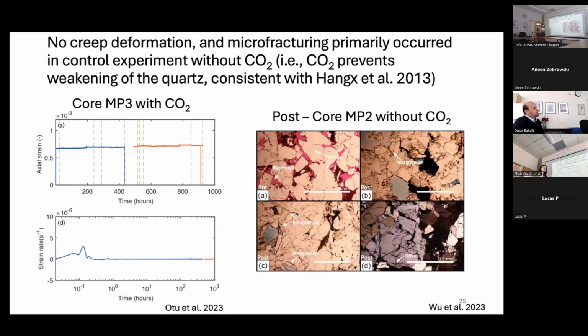Okay, so those are the results from the flow-through experiment. These are the results from the creep flow-through experiment. So we add another element. You remember we have strain measurements too. So that can give us some information about not only chemistry, but also mechanical properties. These are the bulk modulus. From these strain measurements, we were able to calculate the bulk modulus. We didn't show the bulk modulus here because it didn't change much during the experiment. So that's why I'm showing the strains. There's not much strain happening. It's kind of always flat. So nothing too exciting about the impact of CO2 on the bulk modulus. We just don't see much bulk modulus change during that creep flow-through experiment.